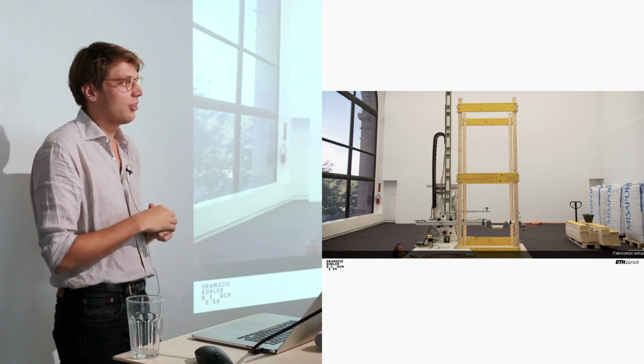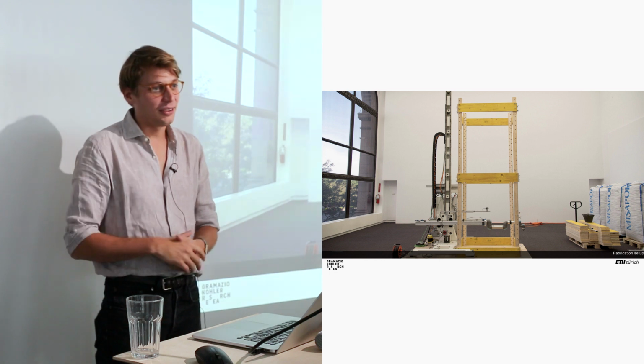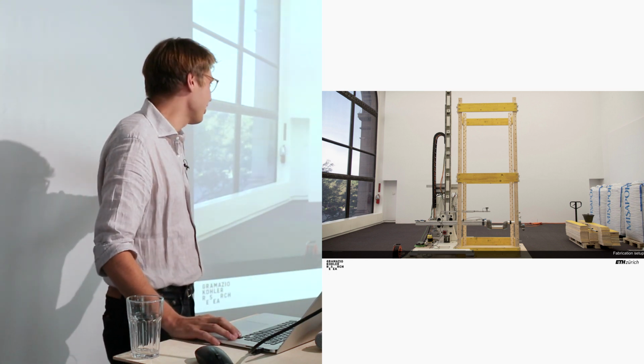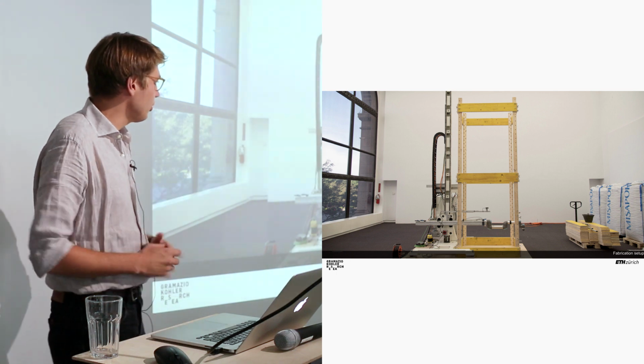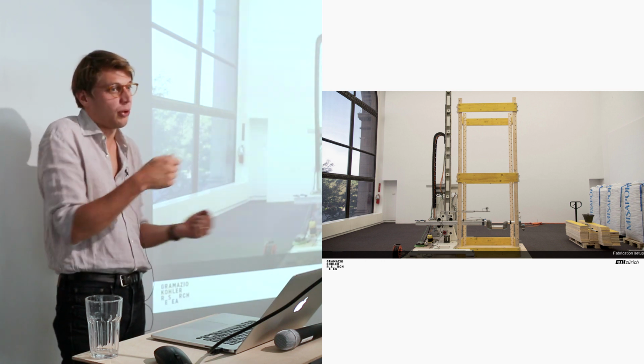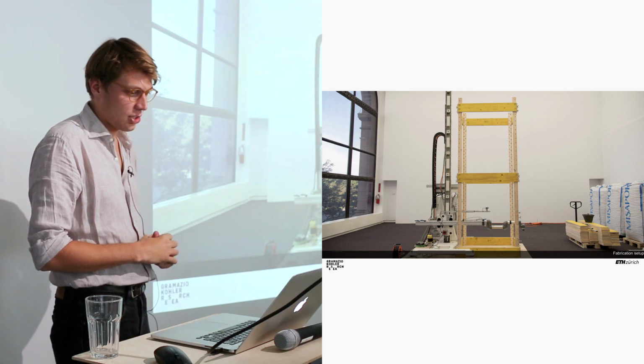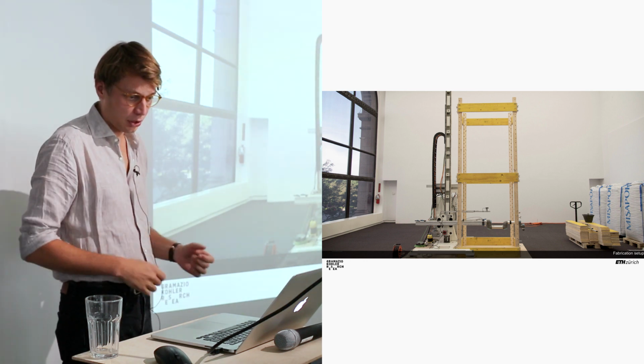And just as a small parenthesis, shipping the robot is not so hard, but wiring the robot is quite tricky. There's a different frequency of the current, and it's actually quite interesting how tricky something so simple can be. We shipped the material also, and when it had arrived, it had compressed by 20%. Due to the super high friction and the rocking of the boat, the material changed. So we had to readapt the pattern when we arrived in Chicago to the size of the new particles.